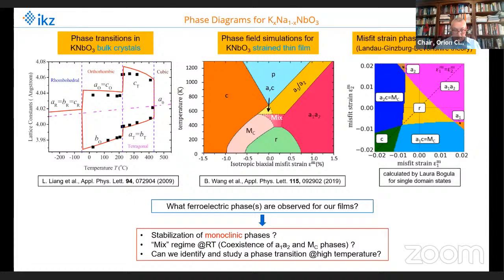So we are interested in phases and phase transitions in our thin films. For bulk crystals, the parameter for phase transitions or for phases is the temperature. However, for thin films, it's not only the temperature, it's also the epitaxial misfit strain incorporated in the thin film. And in the middle of this transparency, the so-called temperature misfit strain phase diagram is shown, where depending on temperature and strain, different ferroelectric phases may appear.